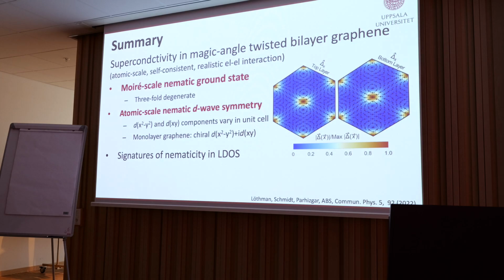Okay, so that sort of summarizes what we found. We're just making one assumption about the pairing. We assumed it was electron-electron pairing, and it's the simplest possible pairing that you can get or model when you go above S-wave pairing. So the simplest anisotropic state. And it's surprisingly complicated. You both have this Moiré scale nematic state, which breaks, let's give you this clear symmetry break in this direction.